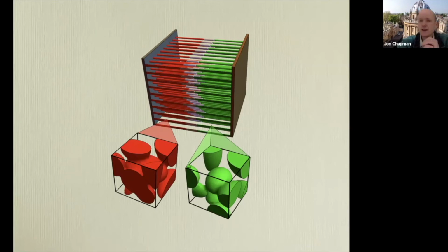If you take that limit, then you turn this three-dimensional model into an array of one-dimensional porous electrode models that are all coupled by the two-dimensional current collectors at the end. So you turn that three-dimensional model into a 2 plus 1-dimensional model.